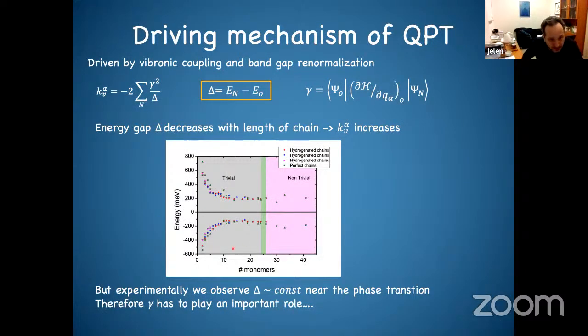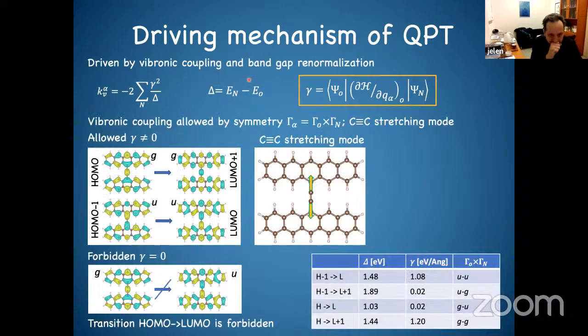And so when we look in our graph where we took different monomers, where we took these band structures, actually what you see here is that this is where the phase transition happens. It's about 25 units. So you see that the band gap is already constant. It means that of course this one contributes to the vibronic coupling, but in the regime when we observe this transition, this band gap is already constant. So it's not entirely driven by this parameter, because typically in all these molecular systems, this is the leading term which makes the stabilization. But then let's have a look at this vibronic coupling.